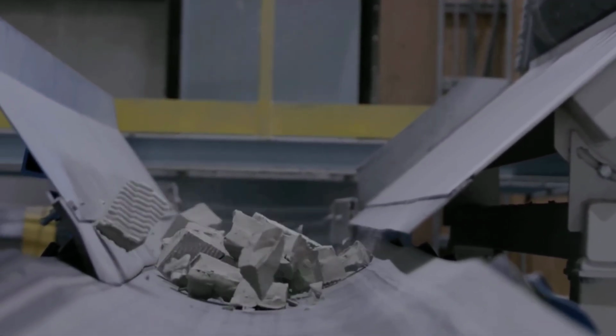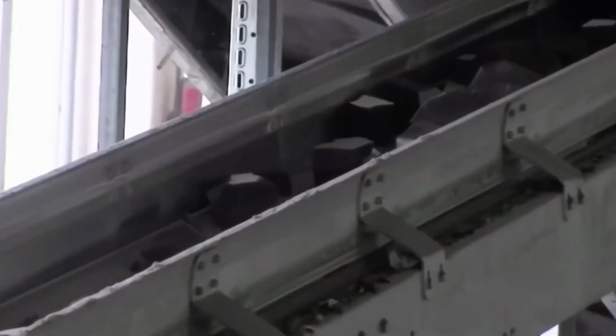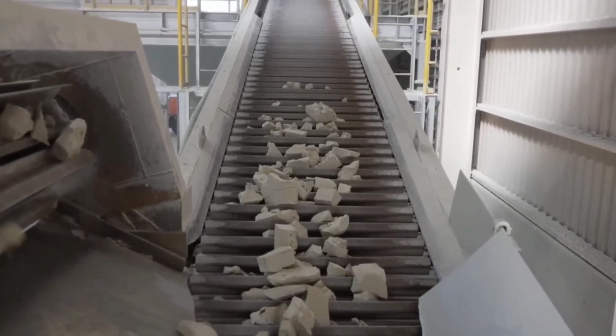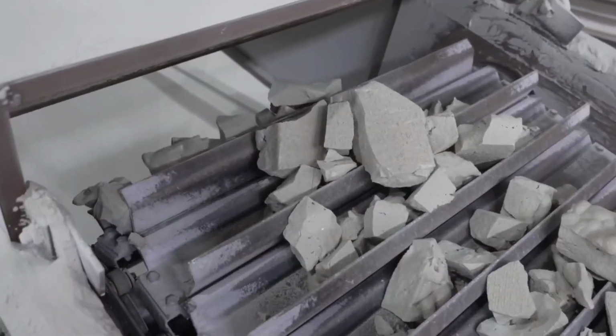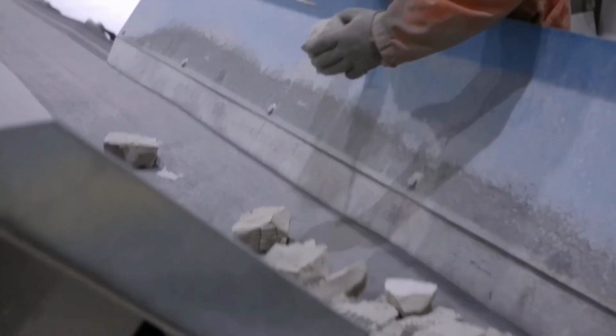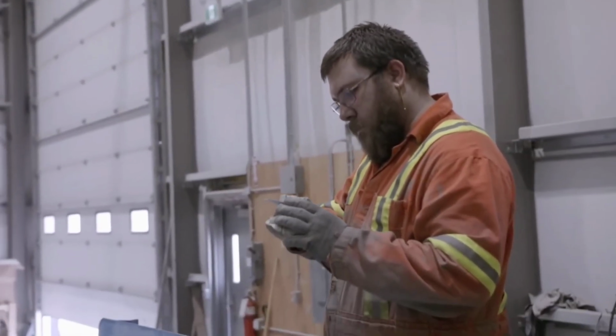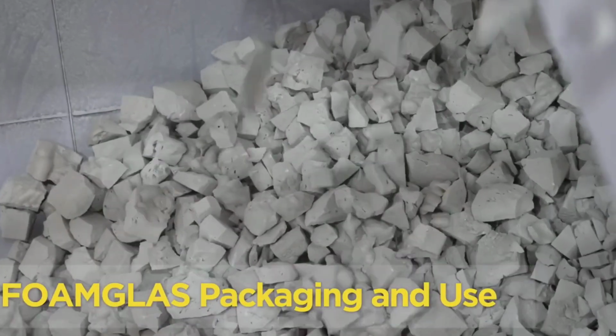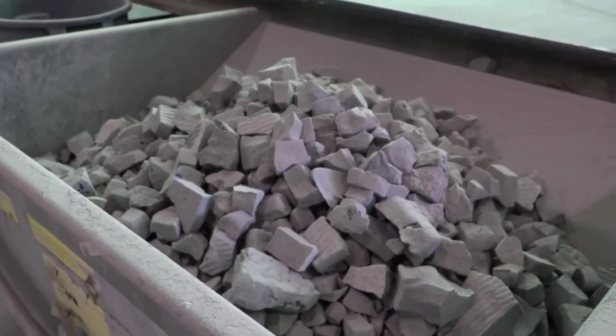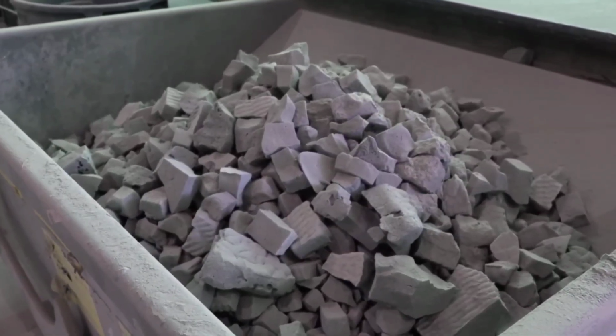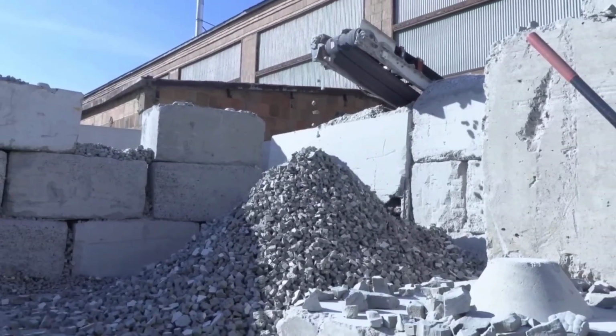The fractured blocks are then collected and fed through an automated sizing system, which sorts pieces by thickness, typically 2 to 6 inches, and density, about 8 to 15 pounds per cubic foot. Smaller fragments or irregular edges are not discarded. Instead, they are recycled back into the grinding and mixing lines, allowing nearly 100% material reuse. In the foam glass industry, breaking is far more than just splitting a slab. It is the moment when a once fragile substance becomes a finished product.